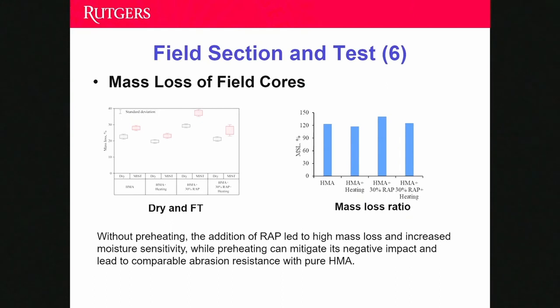From these 2 pictures, we found that the addition of the RAP led to high mass loss and increased moisture sensitivity, which is expected. However, after we apply the preheating, it can mitigate its negative impact and lead to a comparable abrasion resistance with pure HMA.